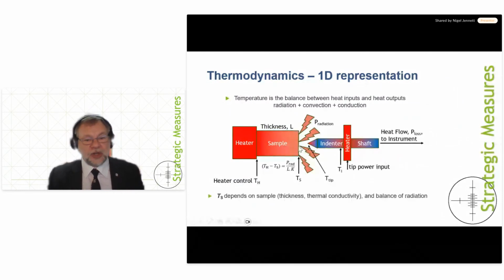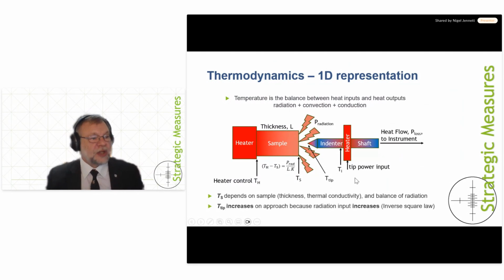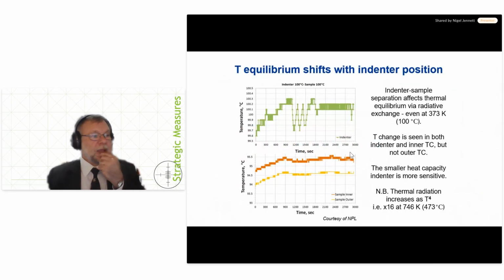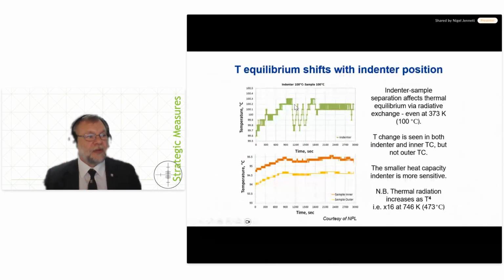this surface temperature changes every time you change the sample. It's a different sample, different thermal conductivity, different thickness, different amount of cement, etc. So it's difficult to find a way you can calibrate the temperature difference of the thing that you can measure here, or even the temperature of the surface that you might measure and the gradient that you might have. The most reproducible thing is to use the indenter, because that is a low thermal mass, a low heat capacity, but it's also unchangeable. If you move backwards and forwards with your indenter, you can actually see the effect of radiation quite readily.